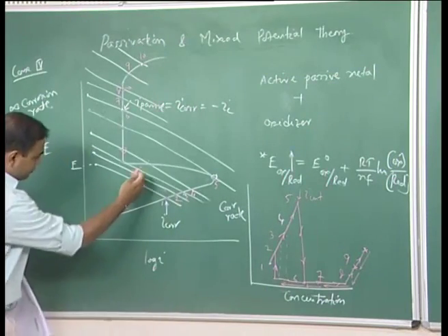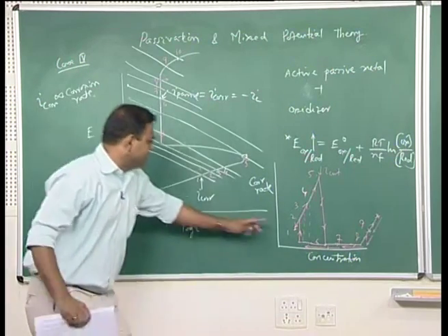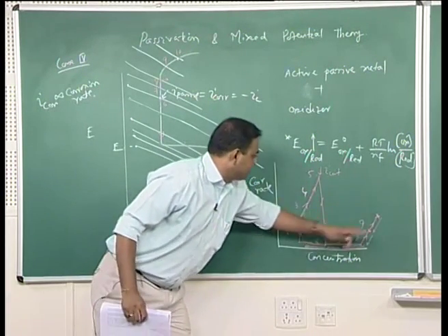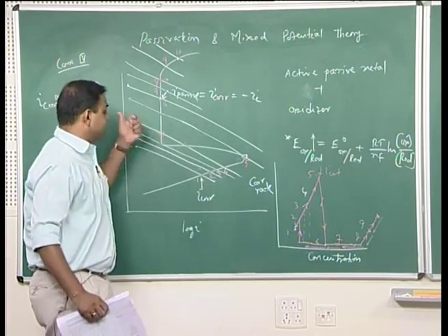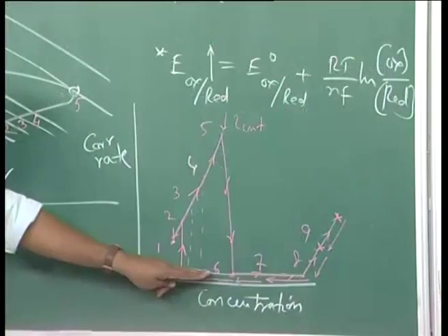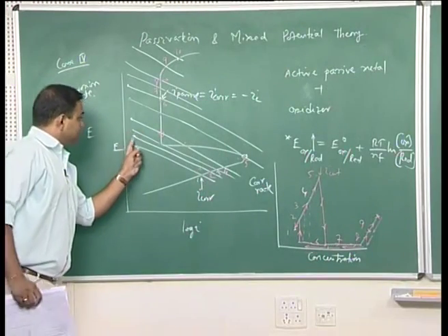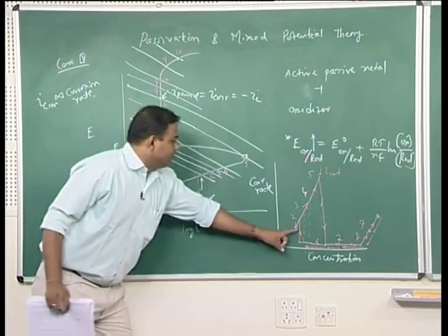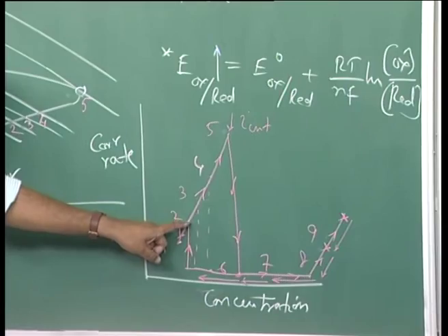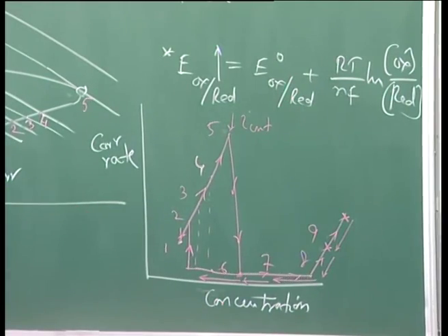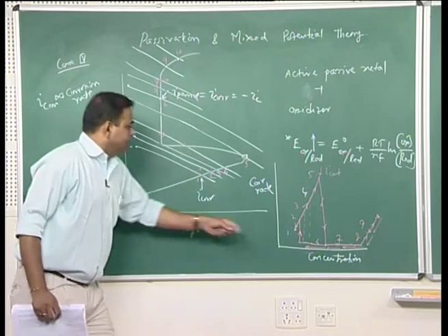And then if you again decrease, it will follow this track. So, while going it is following this track, while coming it is following like this, but at this point we still have the passive layer, it will remain passive, and when we reach the 2nd level, the concentration corresponding to this line, the passive layer is broken, and the corrosion rate will reach the 2nd level.